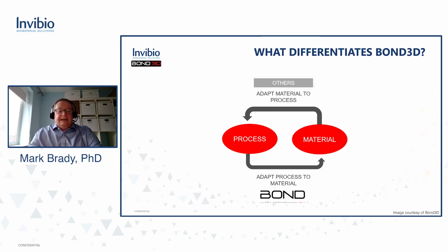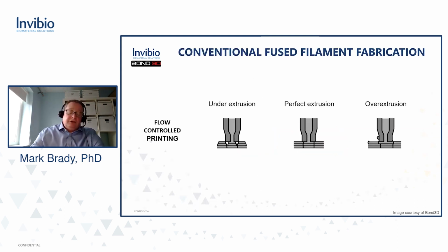One of the things seen in conventional fused filament fabrication is that in an effort to hit perfect extrusion without voids, there's always some fluctuation towards under or over extrusion. Over extrusion can be disastrous. It results in a bow wave of material in front of the print nozzle, and that can eventually drag the whole build off the print bed. And so many printers are calibrated towards a very slight under extrusion.